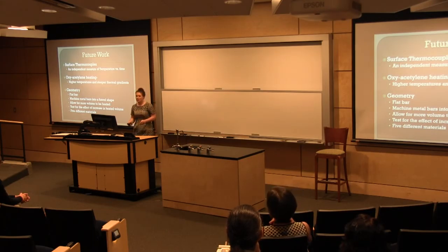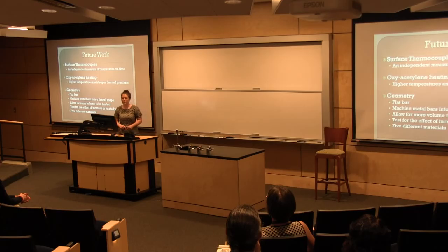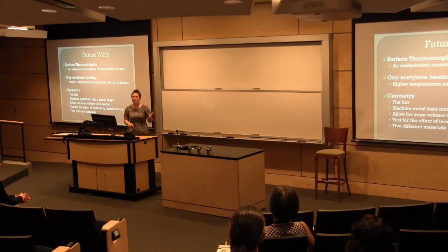In terms of future work, at Aberdeen Proving Ground, we're working to use surface thermocouples, which will give us another measure of temperature versus time, which will back us up with our IR data to have 2 methods of conclusion for that. We're also moving into oxyacetylene heating, which will allow us steeper temperature gradients, as I mentioned before. It's very important to have steep temperature gradients for the phenomenon to actually occur. And then lastly, in terms of looking into geometry, we actually have flat bars in the metals that I mentioned before that are going to be machined into a funnel shape, which will allow for a greater volume to be heated to see if the effect increases with the increased volume.